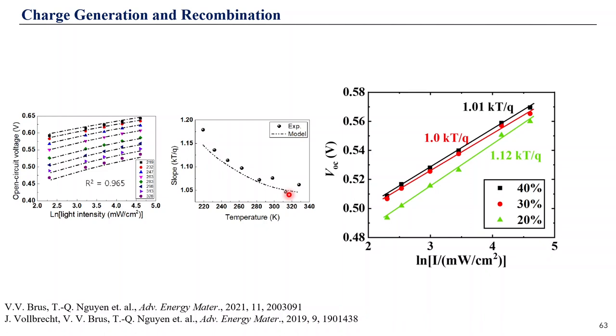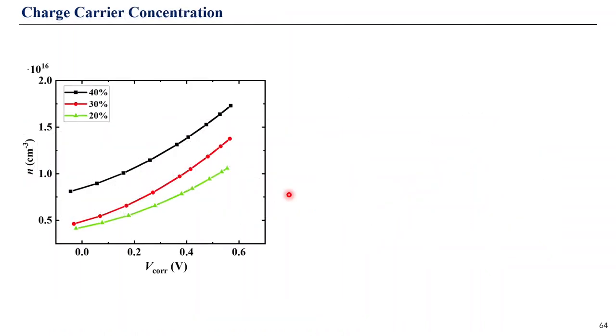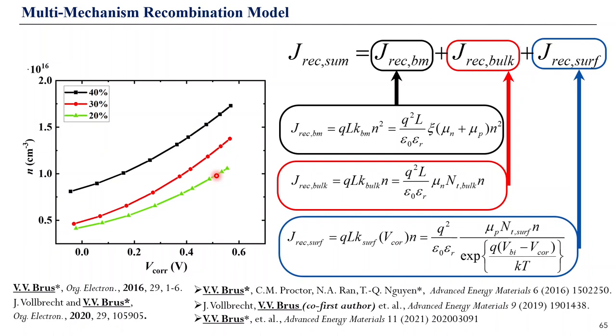However, indeed, we have complex recombination dynamics, and in order to deconvolute what's going on here, we need to first determine the concentration of charge carriers as a function of bias. So we employed voltage impedance spectroscopy to do that. And first of all, I would like to admit that even for the optimized 40% donor content, the concentration is quite low, because on average we get about 10^16 per cubic centimeter. But as we dilute the donor concentration, the concentration of charge carriers drops even further because of the lower generation rate.